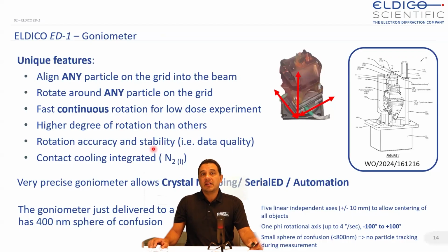Our rotation accuracy and stability is reflected in the data quality, and by contact cooling, we can do low temperature measurements. Our goniometer is very precise, and this is part of the new things that allow us for the so-called crystal mapping, serial ED, and automation, where you don't need to move your beam, but you're moving your motors. At the present time, one of our customers has just received the latest electron diffractometer, and I just see that I didn't optimize this, because right now the sphere of confusion that they have is around 400 nanometers on that device.